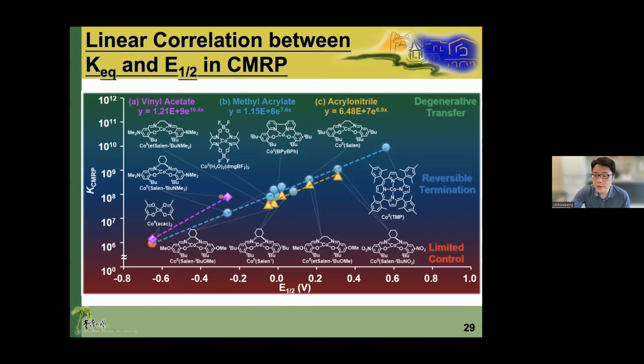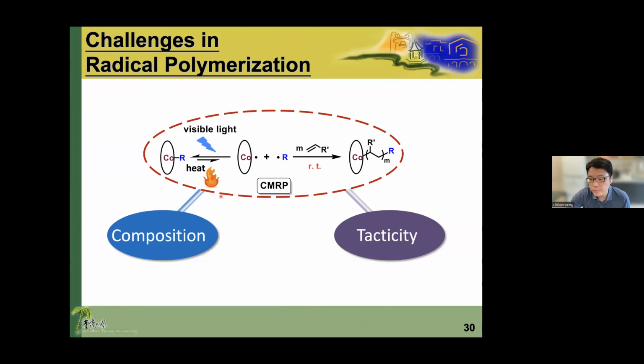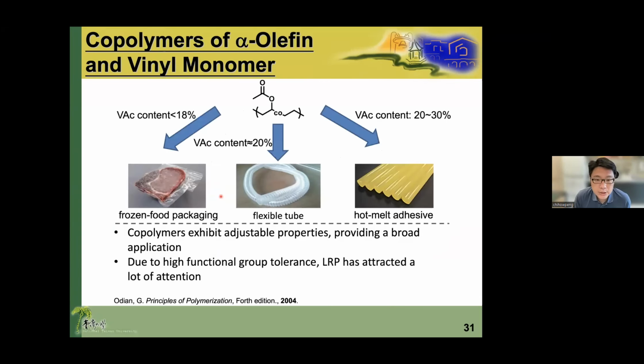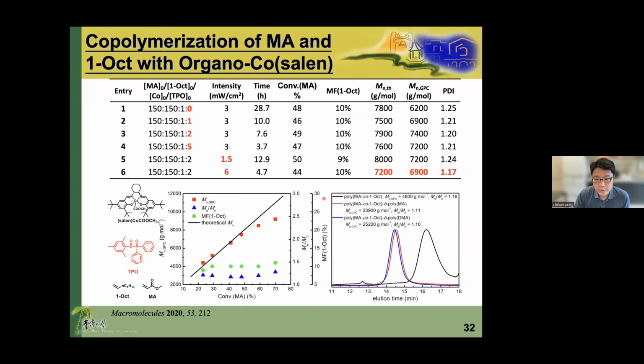And then we try to challenge the holy grail, which means the most difficult things in polymerization: the composition control and the tacticity control. So why do we want to control the composition? Because, for example, in EVA product, if you can change the content of vinyl acetate, you can largely change the physical property of your product. You can see they are totally different things. So we try to use this cobalt system to approach the controlled radical copolymerization, and we use 1-octene and acrylate.